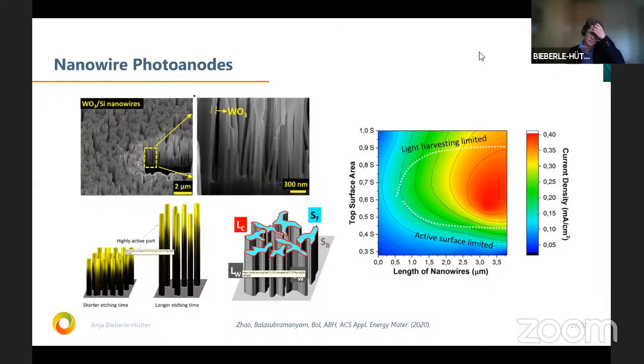So the PhD student who did this work went then one step further to make nanowire photoanodes, and you see here SEM images of these. We also prepared different lengths of the nanowires, and then we found if we etch them that we get different top surface area. So top surface area is actually when you look from the top how much area there is, and this is an important parameter. And when we draw this now in 3 dimensions, the current density, we see that it's really a trade-off between nanowire length and this top surface area.